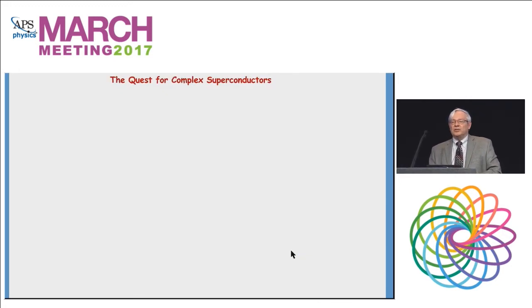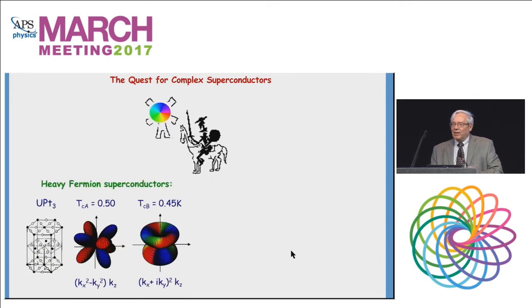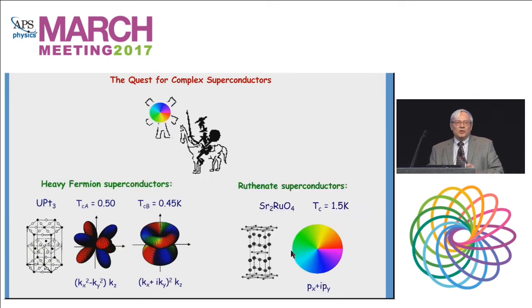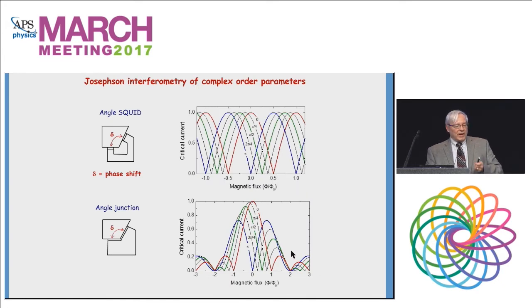But luckily, there are other superconductors that are complex. I spent a lot of my career trying to look for these. The two big candidates are heavy fermion superconductors and the ruthenate superconductors. Heavy fermion superconductors, I should point out first, the way you can tell this is if you have a phase shift other than zero or pi, some kind of a shift between zero and half a flux quantum. If you use a single junction, you see this node lift in the middle, or depress in the middle, as we said before, but in all cases, you get something that breaks parity symmetry.